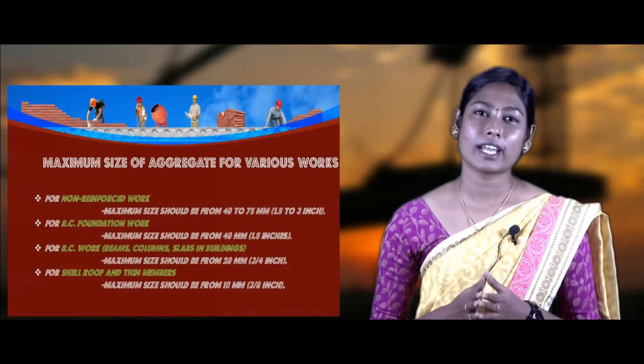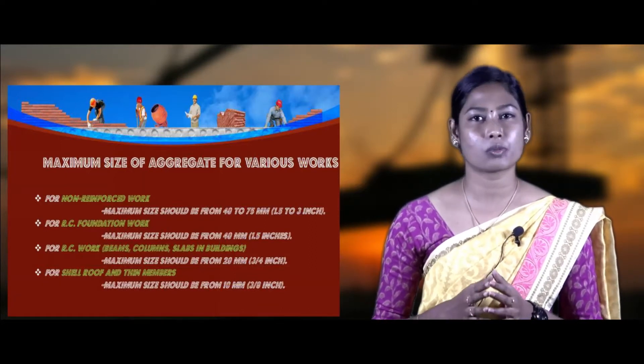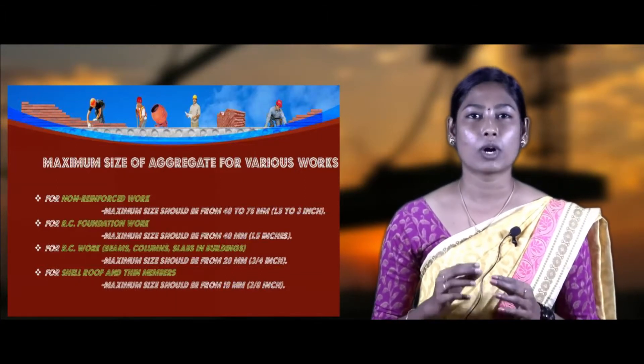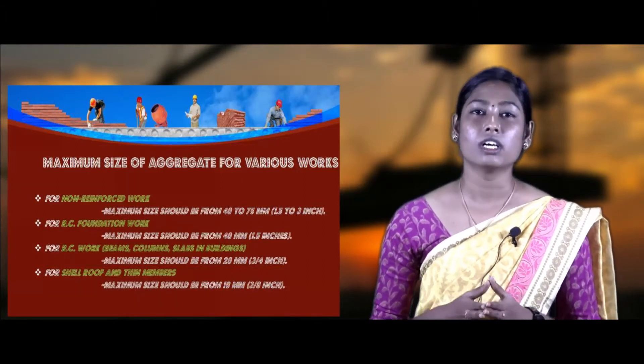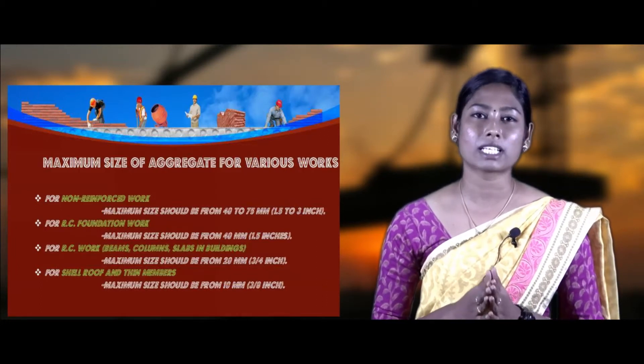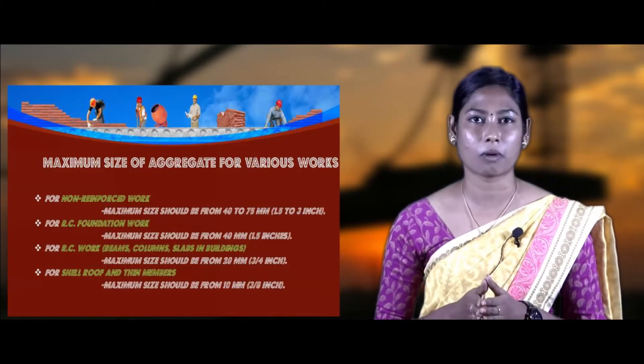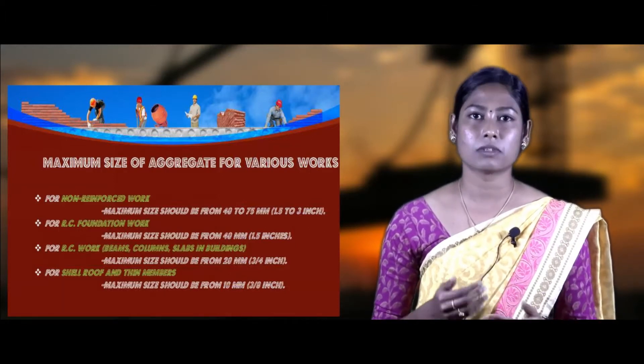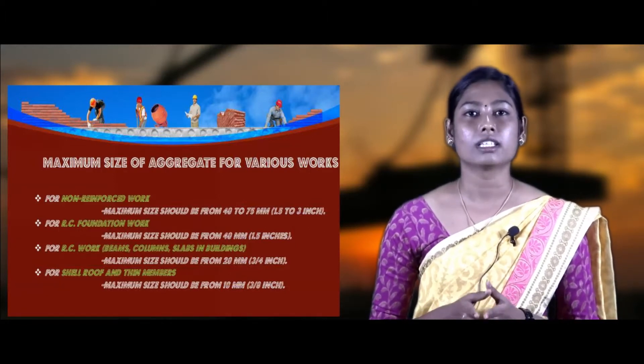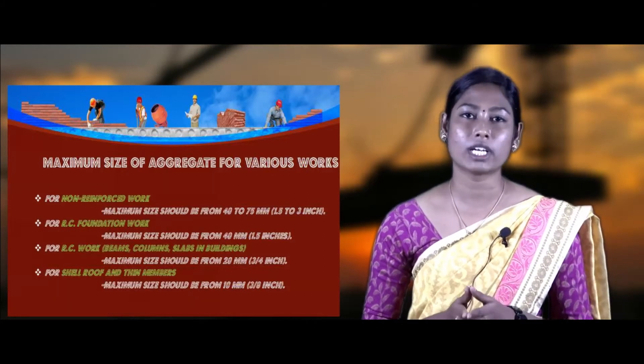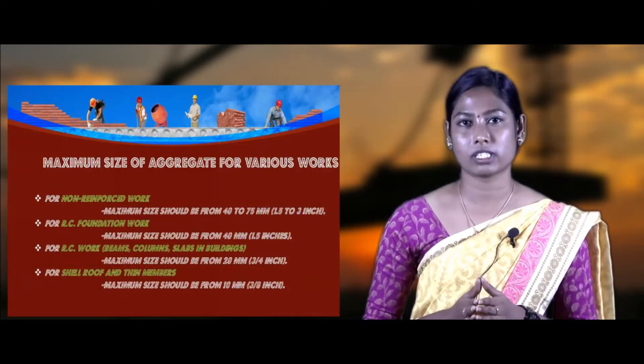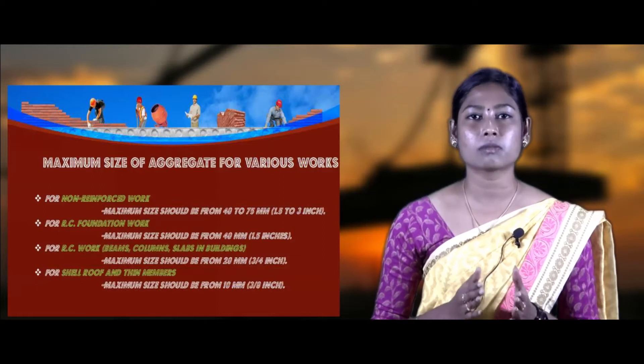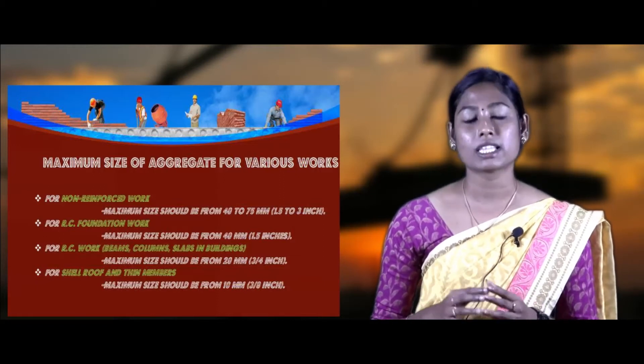The maximum sizes of aggregates used for various work are as follows: for non-reinforced work, the maximum sizes should be from 40 mm to 75 mm (1.5 inch to 3 inch); for RC foundation work, the maximum sizes should be 40 mm (1.5 inch); for RC work such as beam, slab, and column in buildings, the maximum sizes should be 20 mm (3/4 inch); for shell roof and thin members, the maximum sizes should be 10 mm (3/8 inch).